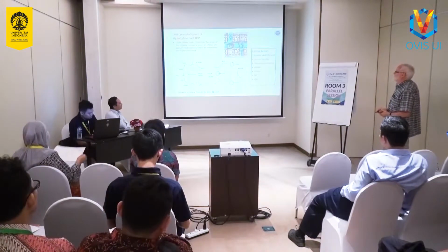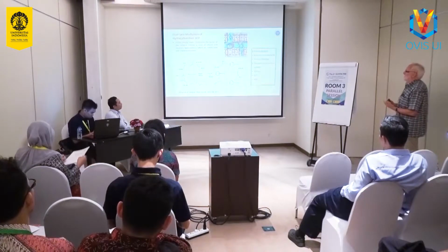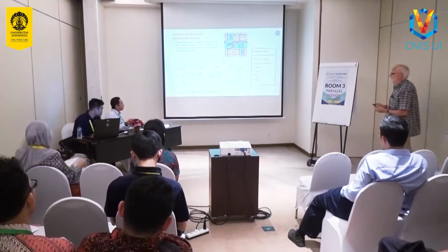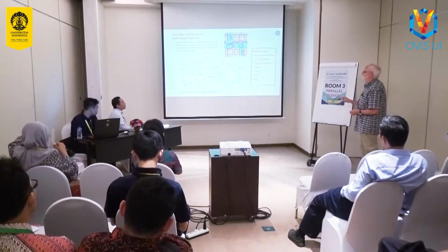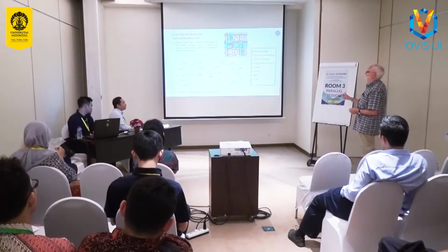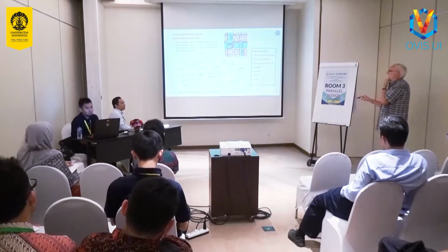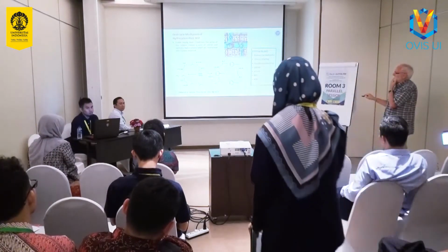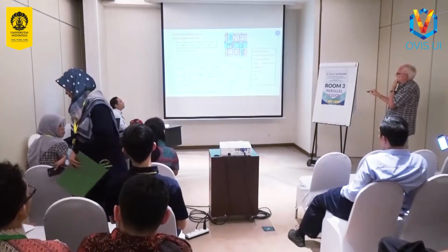Now, there's been a lot of work already on this, and under steady state conditions, it's widely believed that the mechanism is a complicated dual cycle, where you have a complicated mixture of olefins and aromatics in the pores of the zeolite, which undergo successive methylation and cracking to produce the gasoline range hydrocarbons. So this is the steady state of the working catalyst, and here's some of the evidence that's in the literature for this.